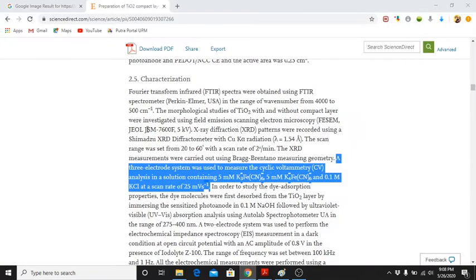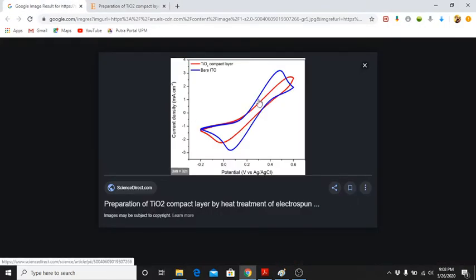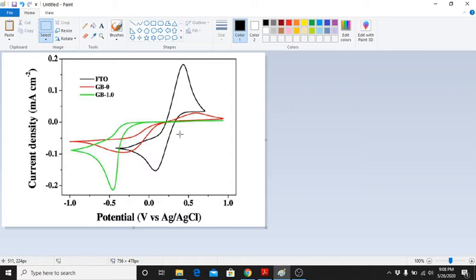So also from my paper, you can see that with a compact layer, there is no apparent anodic peak, or the anodic peak is reduced compared with the bare ITO. So why did this happen? Why does our main material with TiO2 compact layer or whatever compact layer display a reduced anodic peak? Because a low recombination process is a good one. We want to have a low recombination process. Having a lower anodic peak or no apparent anodic peak is good, because basically we must go back to the basic thing, oxidation.